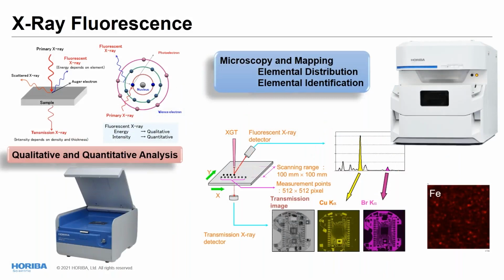Let me start with X-ray fluorescence, or XRF. XRF is a technique that requires little to no sample preparation, and is able to measure qualitatively and quantitatively elements from aluminum to uranium, some systems being able to go down to carbon. The technique is based on the detection of a fluorescent X-ray emitted by the elements after irradiation of the sample with a primary X-ray source. The energy of each detected X-ray is characteristic of the elements, which helps to do the qualitative analysis, and the intensity is proportional to the number of atoms, and then to the concentration in the sample, to provide quantitative data.